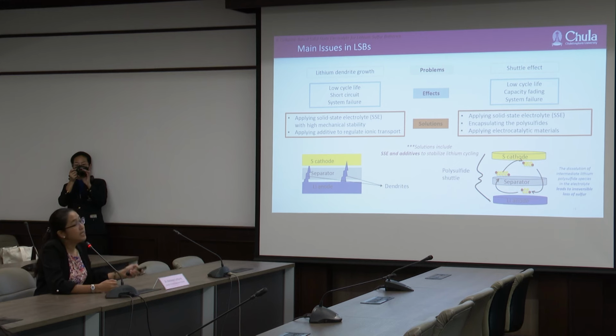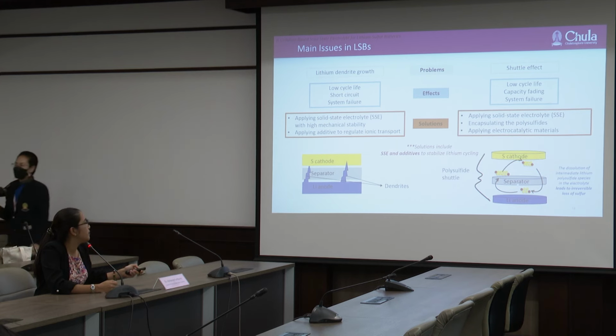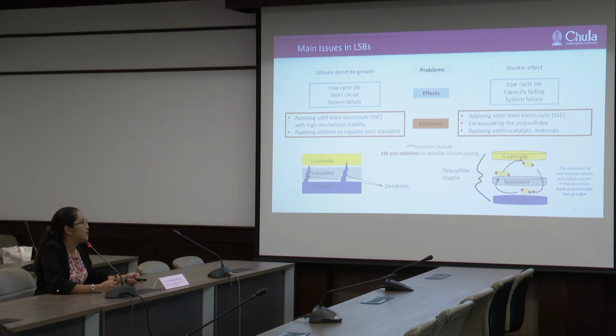So the main issues in lithium-sulfur batteries include lithium dendrite growth, which can cause a short circuit and system failure. Another one is the shuttle effect, that is, the dissolution of intermediate lithium polysulfide species in the electrolyte system, and this leads to irreversible loss of sulfur. So solutions include solid-state electrolytes and additives to stabilize lithium cycling.